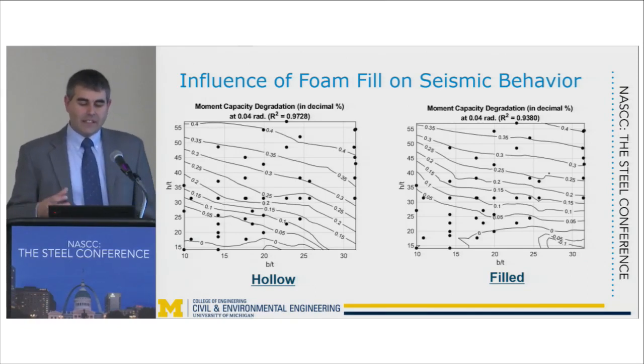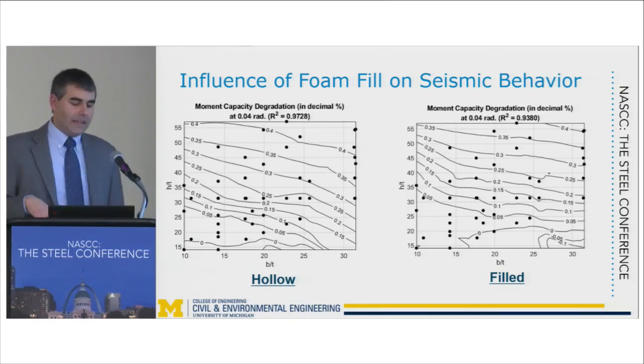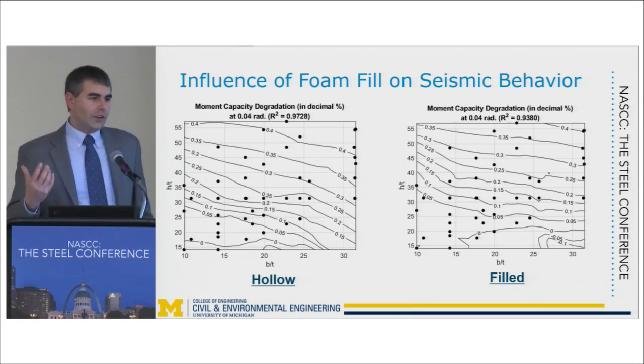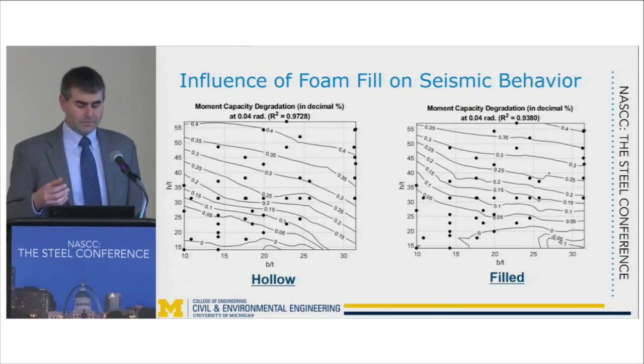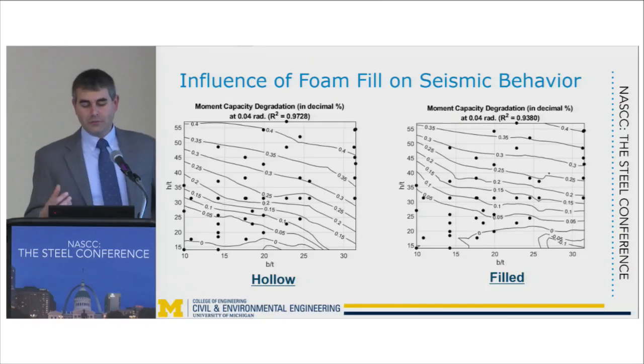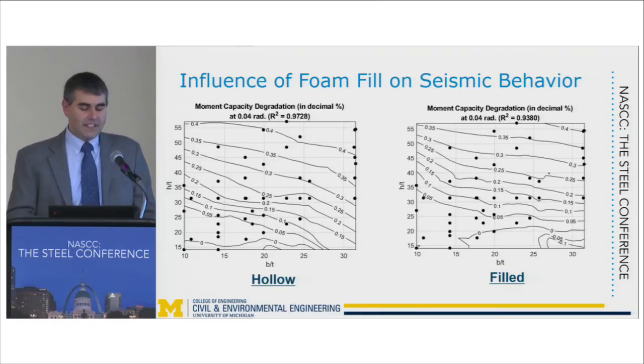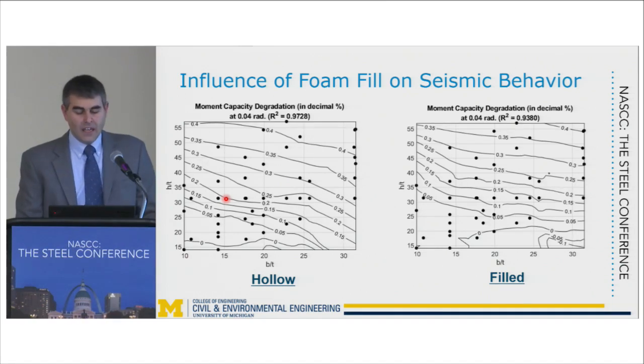So again, based on that, we calibrated some detailed finite element models and then looked at what level of depth to thickness ratio and width to thickness ratio, if we have the foam fill, will allow us to reach 80% capacity out to 0.04 radians. So essentially what you're looking at here is plots of the moment capacity degradation at 0.04. And if you look at that 0.2 line, that would essentially give you your depth to thickness and width to thickness limits for a special moment frame.